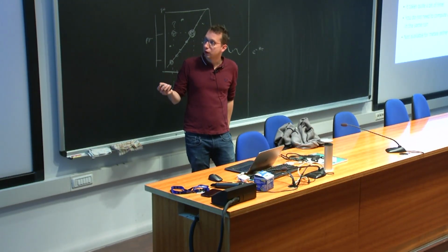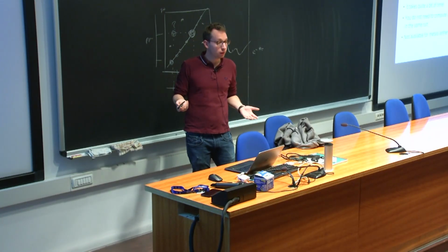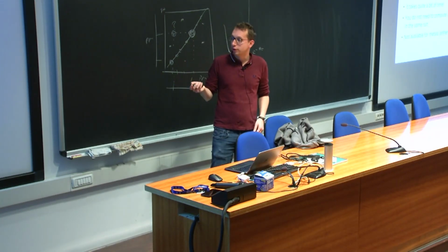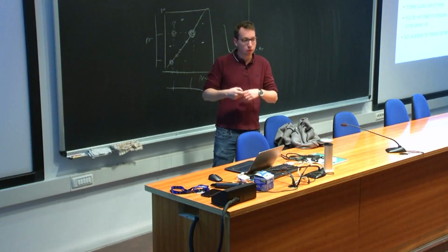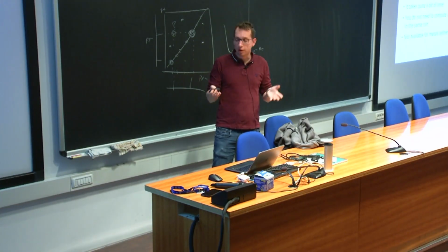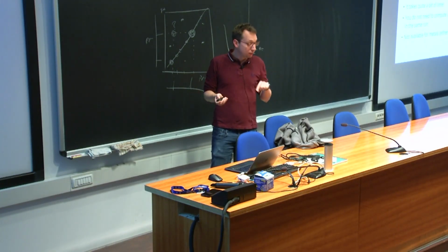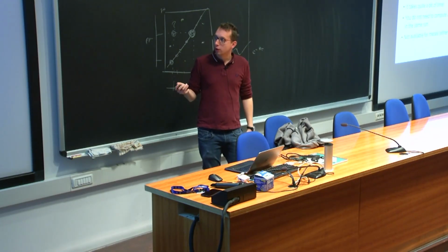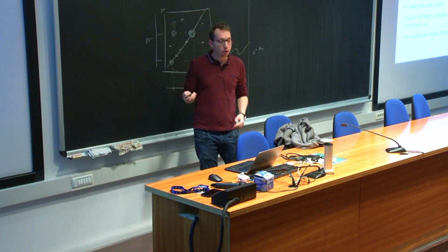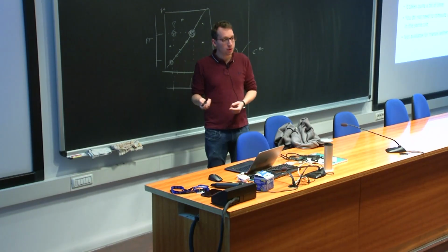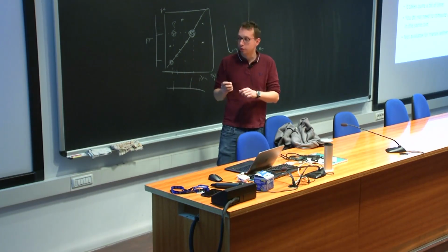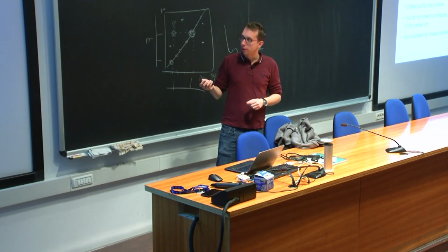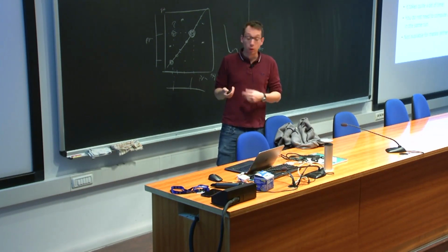So of course, calculation of epsilon is not available for metals. We know that metals have infinite dielectric constant because they polarize, like they screen perfectly any electric field. However, the phonon code does not know if what you are computing is a real metal or it's going to be an insulating molecule, and you just put a small smearing to help convergence. And it will complain, it will stop anyway. So, well, if you can do the calculation without smearing, it's better.